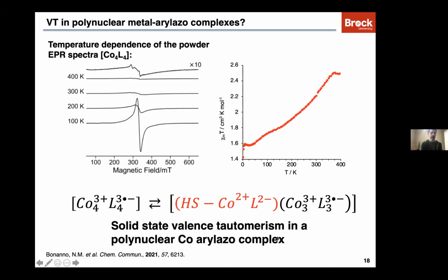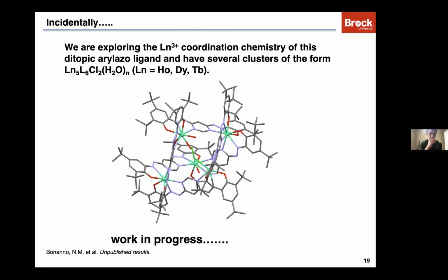Clearly have a valence tautomerism occurring in the system. Now, we've measured the conductivity of this complex's single crystals, and there is no conductivity. It's an insulator. So we haven't established any conductivity with this system, but incidentally, I know lots of people are interested in lanthanide coordination chemistry of these types of ligands, and we've made several lanthanide complexes of this ligand that have this same type of pentanuclear form.